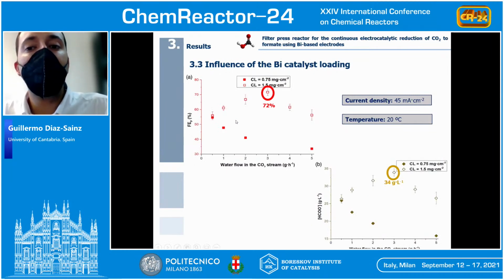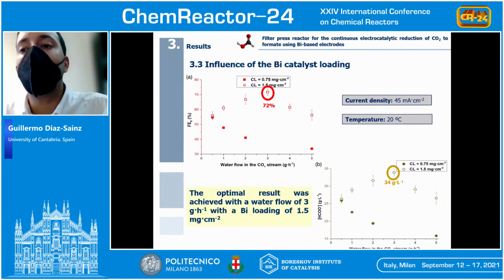About the influence of the bismuth catalyst loading, in this section we studied the influence of doubling the catalyst loading from 0.75 to 1.5 milligram per square centimeter, and the current density used for this experiment was 45 milliampere per square centimeter and a temperature value of 20 degrees, which is considered the optimal value for the electrocatalytic reduction of carbon dioxide to formate. We can observe that working with a catalyst loading of 1.5 milligram per square centimeter, the optimal value of water flow is 3 grams per hour, obtaining a Faraday efficiency for formate of approximately 72% and a formate concentration of 34 grams per liter. It is important to highlight that in general, when increasing the bismuth catalyst loading, it is needed to increase the amount of water in the carbon dioxide humidified input stream, because it is necessary to achieve a trade-off in the gas-liquid-solid reaction system equilibrium.